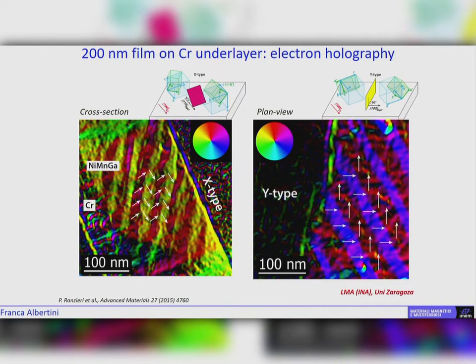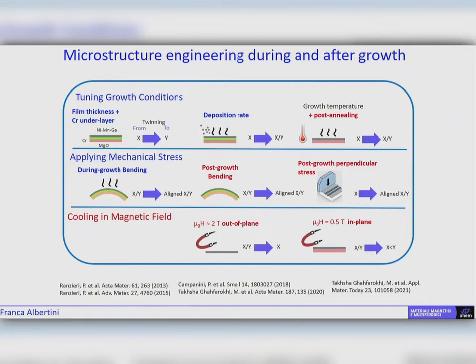The orientation has been checked with electron holography that has allowed to correlate the magnetization orientation with the twin and the microstructure of these materials. And we have gone on by exploring the possible microstructure engineering. So by changing the thickness and the underlayer, we are able to change from one kind of twins to the other by changing the deposition rate, and also by suitable post-annealing. We can align and induce change by applying a mechanical stress, both during growth and after growth.